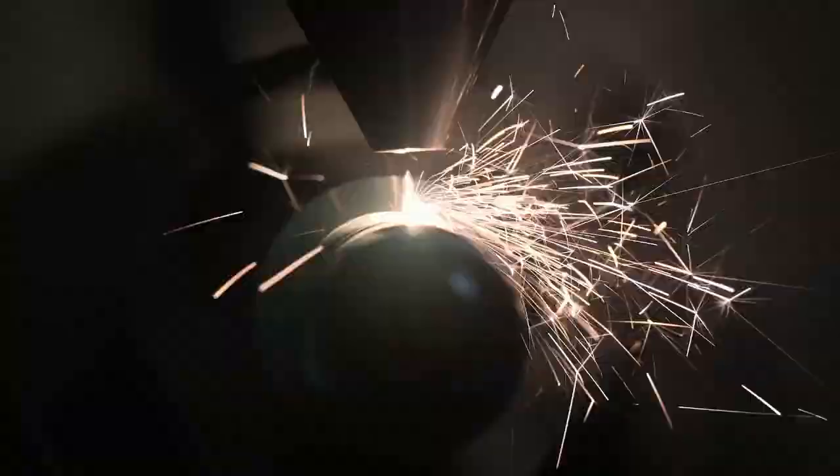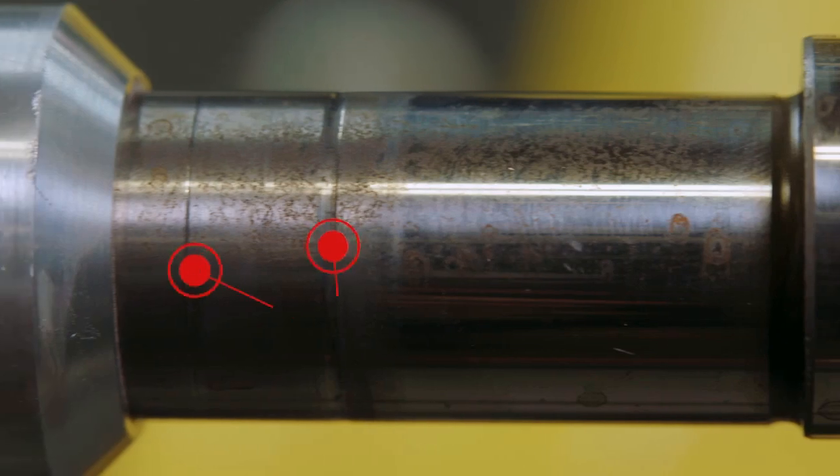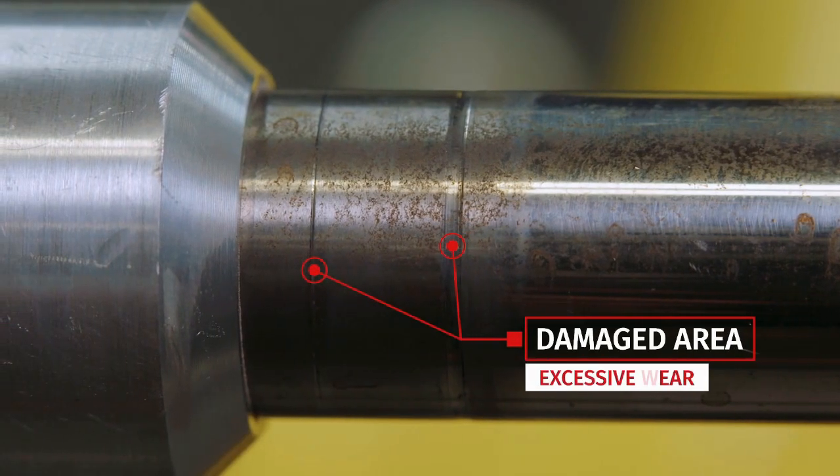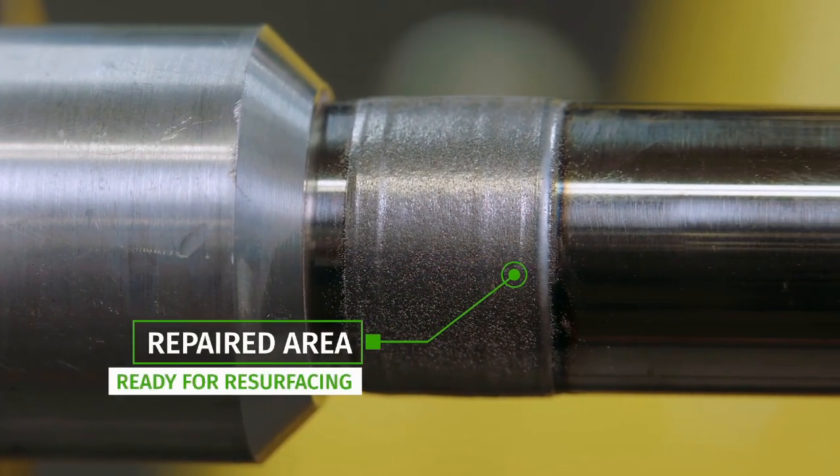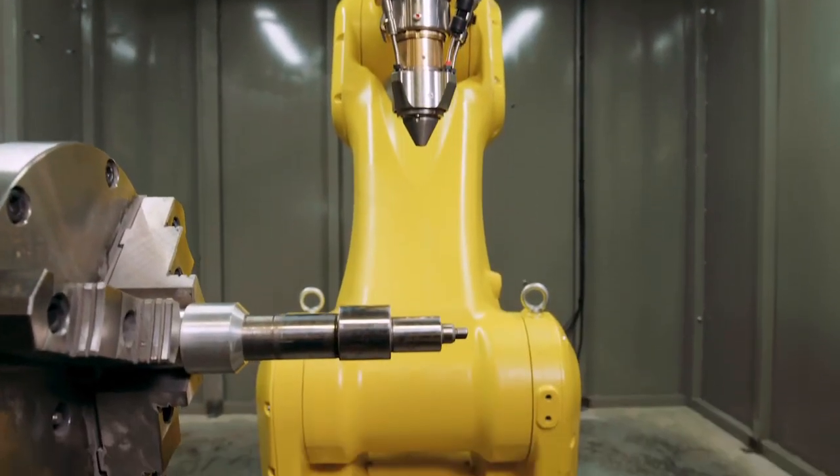The focal point on this is a one millimeter diameter dot. This allows us to build up very small damaged areas without disturbing the metallurgy or the previous heat treat. We can fix the part without disturbing the part any more than is absolutely critical.